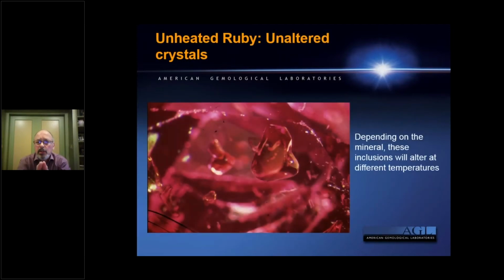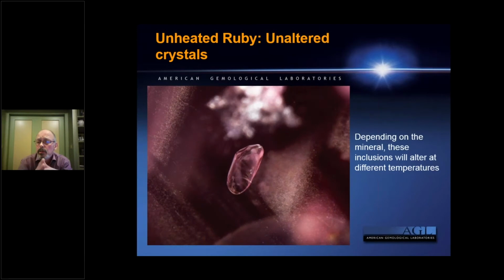So we're going to look at things like carbonate crystals, calcite crystals, pristine, transparent calcite crystals like you see here and like you see here. These are mineral inclusions which alter even at relatively low temperatures. You're going to see signs of alteration. So inclusions such as this provide more information about whether a stone has been heated or not.